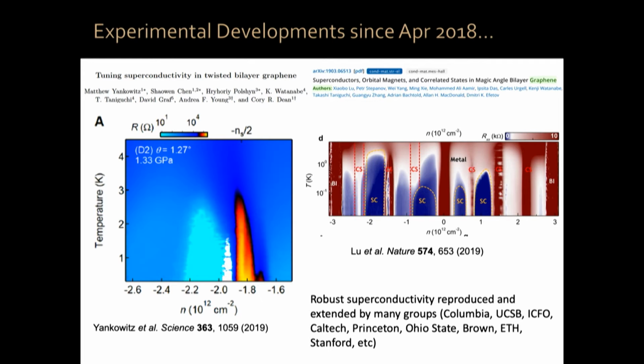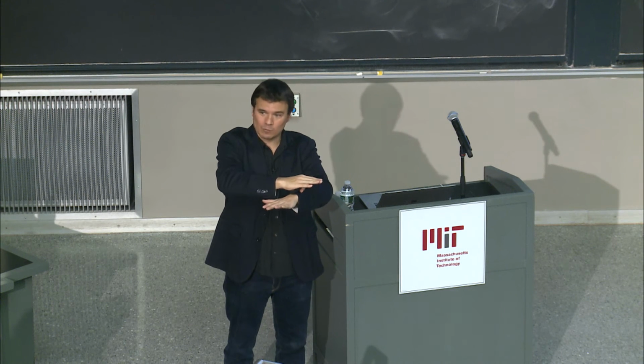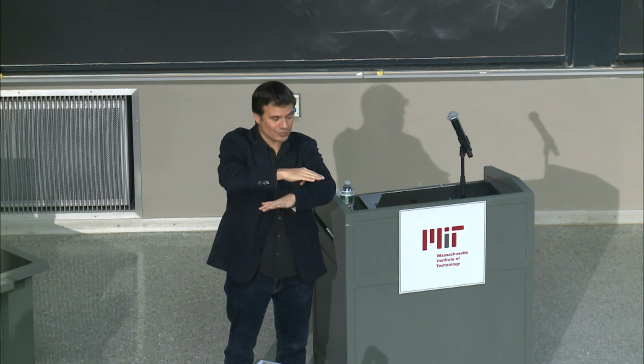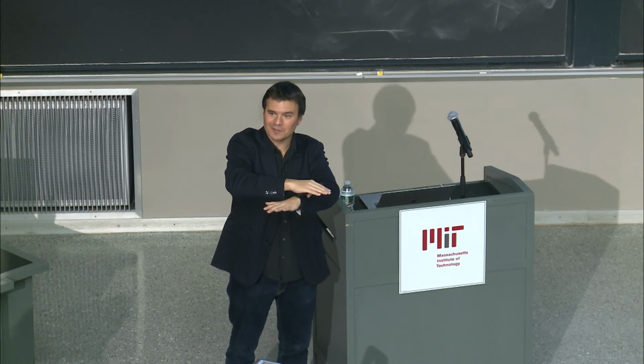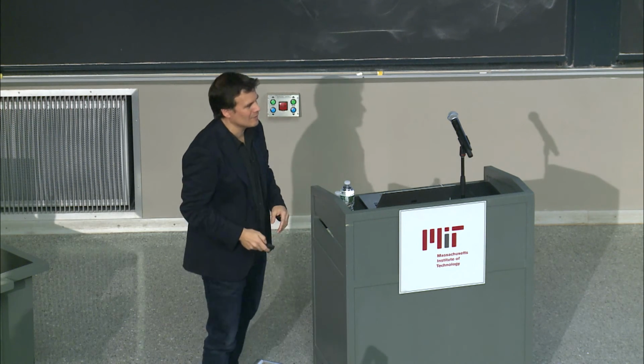Remember that this magic angle condition depends on this interlayer tunneling. So when you apply pressure, you change that tunneling between the electrons. And they were able to make devices at a larger angle, which was not magic, but then you apply pressure, and that angle became magic, okay? And they saw superconductivity, etc.